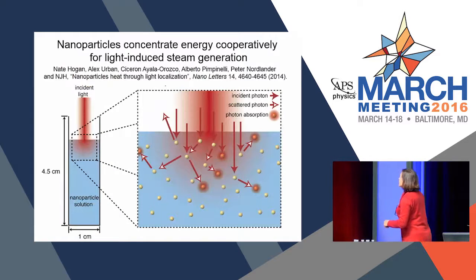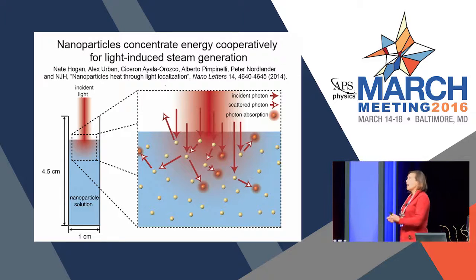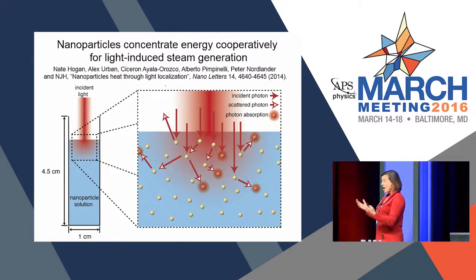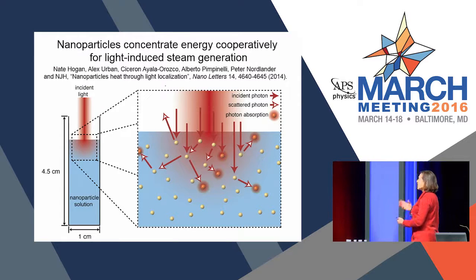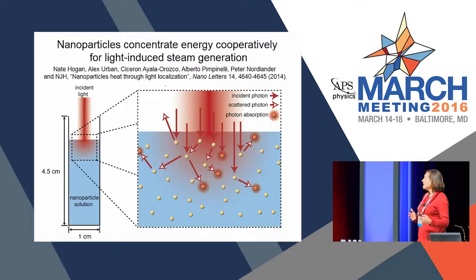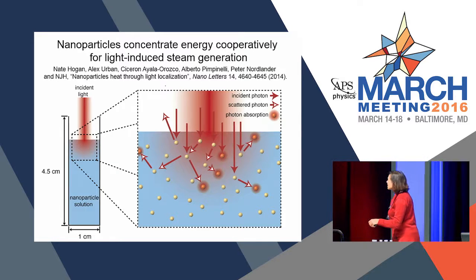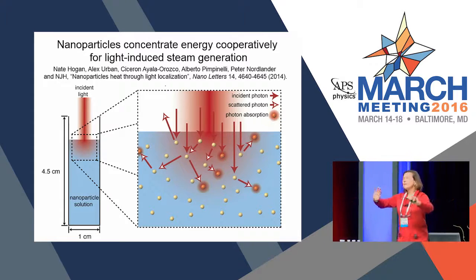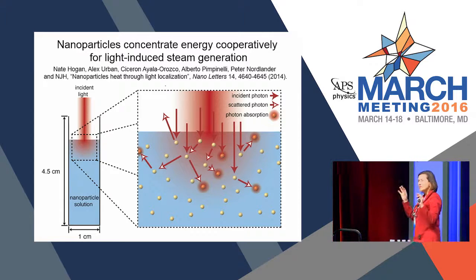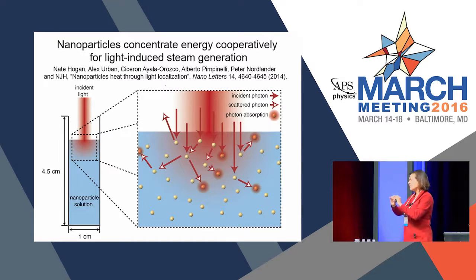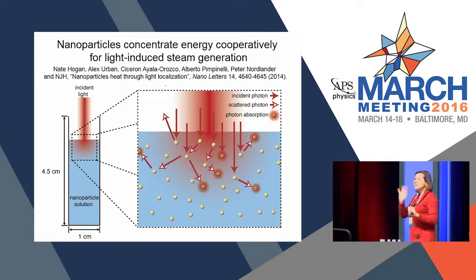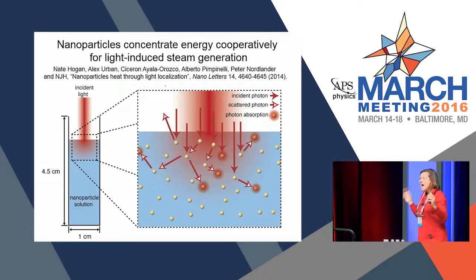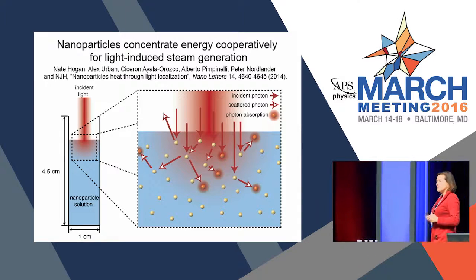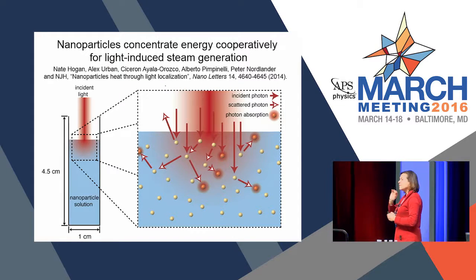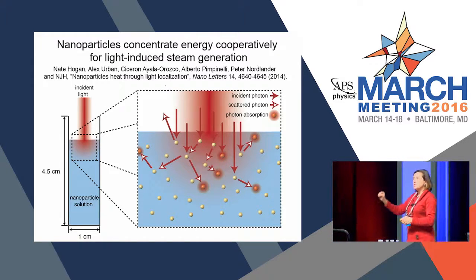So what could be going on? It turns out that what's going on is a very interesting, basically a lesson in optical trapping, or for some people, you can think of this as a variant on the weak localization of light, where we have a solution of nanoparticles. In the world of weak localization, some of you might study this, you look at the light scattering properties of particles, but you always make sure that those particles are lossless. Well, here we have to have loss. We have to have absorption because that's what drives this particular effect. So we're looking at this type of light localization in a regime where physicists typically don't want to study at all, and that is where the particles both are absorbers and scatterers of light.